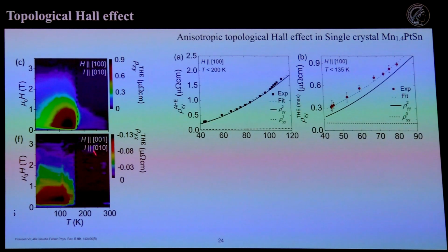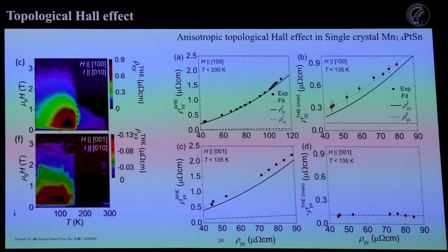And so we did the analysis for the top one. I showed him how to take out the anomalous Hall effect. The anomalous Hall effect is very intrinsic. You have this quadratic dependence in the resistivity, and you have some small skew scattering there. Then he also did it for the topological Hall effect part that he subtracted. He got the strong quadratic case, so it's pretty much an anomalous Hall effect. But when he did it for the 001 direction, he saw for anomalous Hall effect, quadratic behavior with a bit stronger skew scattering term. But for the topological Hall effect, he saw this completely flat line.